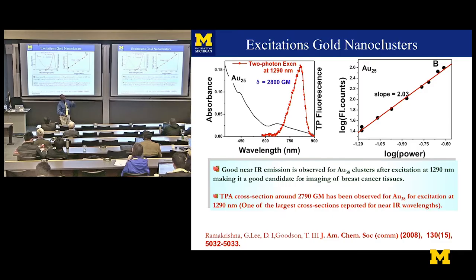And if you look at the two-photon process, it's basically a process in which two photons of the system are absorbed before one of them relaxes, right? You absorb two photons, and you look at the emission afterwards, the so-called two-photon absorption measurement, fluorescence. And you can see it's got some really strong two-photon absorption out here in the 750 region. That's why there was some interest in looking at these for imaging. And it's good in the near IR.